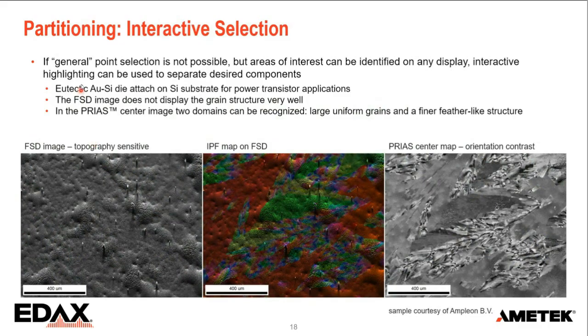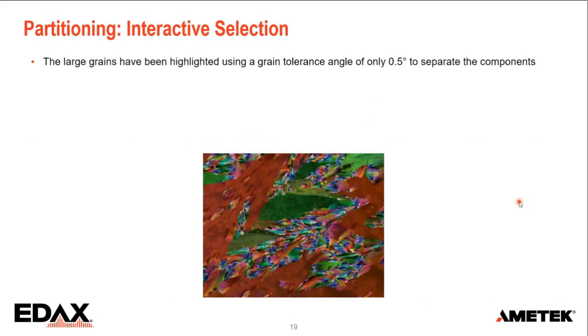So the image that I have here is an EBSD map on eutectic gold silicon die attach for power transistor application. So it's a silicon substrate with a gold coating on top. You can see some topography. Here in the middle, we have the IPF map. We can see the color coding very nicely. And here on the right, in a PRIAS image, we have a very strong indication of orientation contrast. So we can recognize the big grains. We can recognize the small feather structure of the small grains. And I would like to separate those.